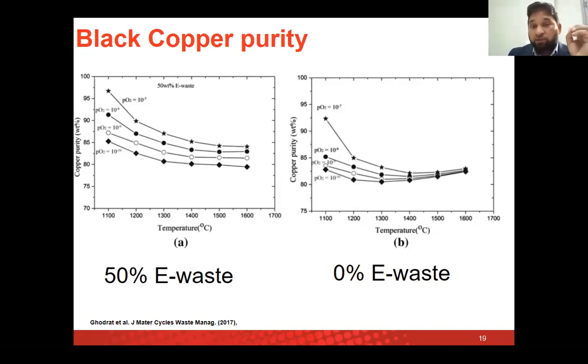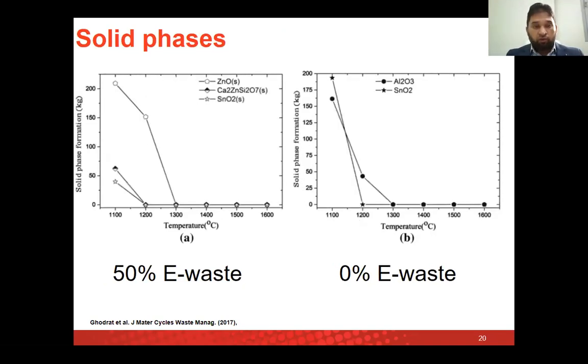So the black copper is not a pure copper. Okay, black copper composition, the concentration of copper in black copper is about 85 to 90%. But you have other elements, like zinc, lead, nickel, gold and silver, all in solution in the black copper. So here, during the reduction processes, the challenge that is faced with electronic waste is also that some kind of spinels form. I mean, one, of course, zinc oxide is the solid phase there. To minimize that zinc oxide or other solid phases, you need to increase temperature. That again is also challenging. It's not that straightforward and simple.